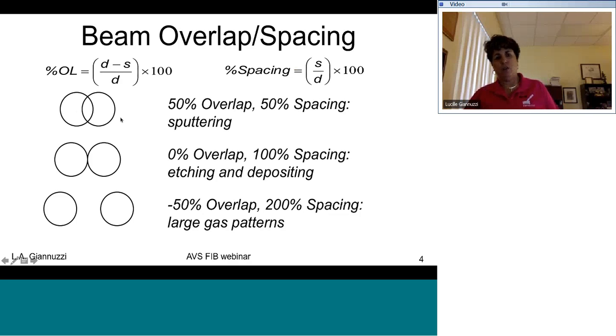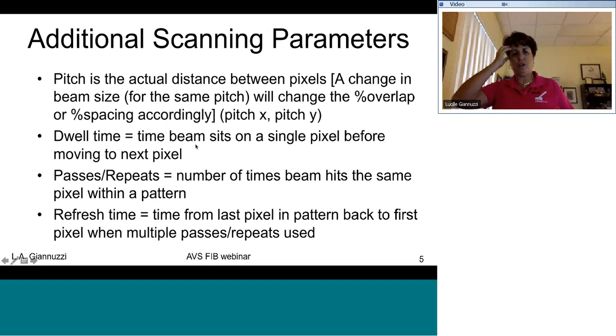And so we use the overlap or the beam spacing differently depending upon what we want to do, whether it's milling, deposition, or etching. Okay, some other parameters: pitch or the step size is the actual distance between pixels. So again, a change in beam size for the same pitch will change the percentage overlap or the percentage spacing. We can change the pitch in either X or Y or both. Some other parameters: dwell time is just the amount of time that the beam sits on any single pixel before moving to the next pixel. The passes are repeats, so the number of times the beam hits the same pixel within a pattern. And the refresh time is the time from the last pixel in the pattern back to the first pixel when multiple passes or repeats are used. And all of these functions are extremely important depending upon the function.